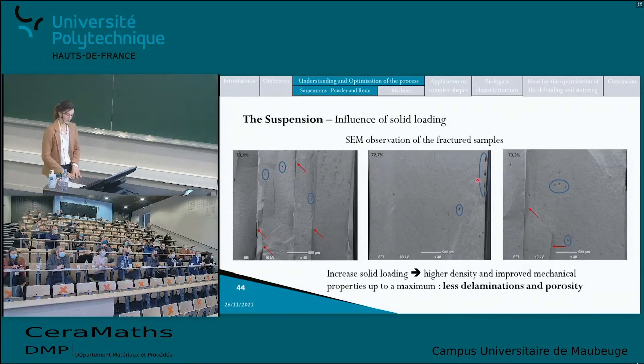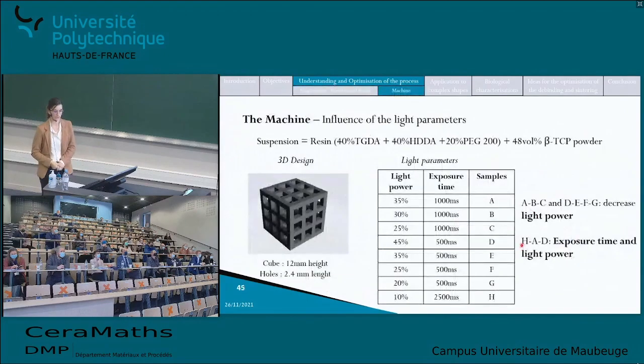So the next step was to evaluate the influence of the light parameter, choosing again the best resin. And I decided to stay with 48 volume percent of beta-TCP powder to pursue the experiment. So I printed again the cube with holes, this time with the goal to measure the precision of the size of the holes in the printed parts.